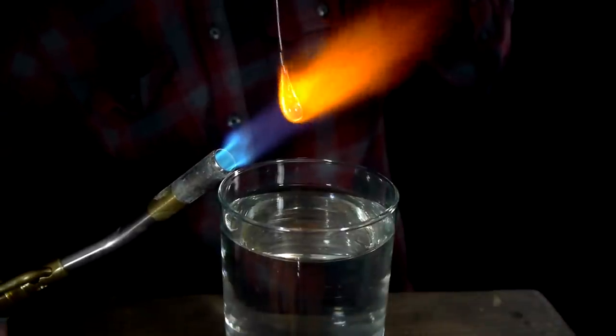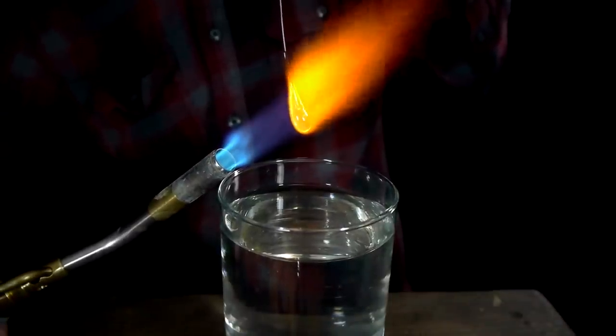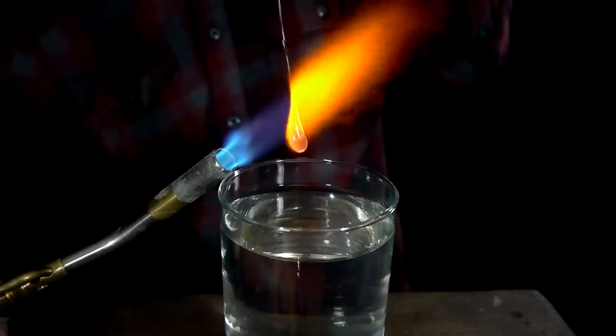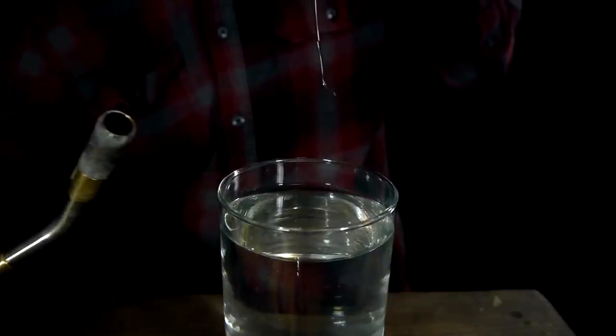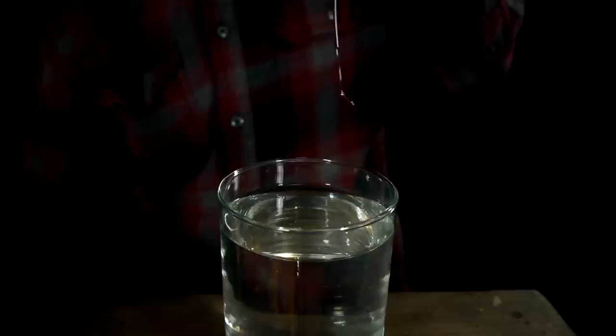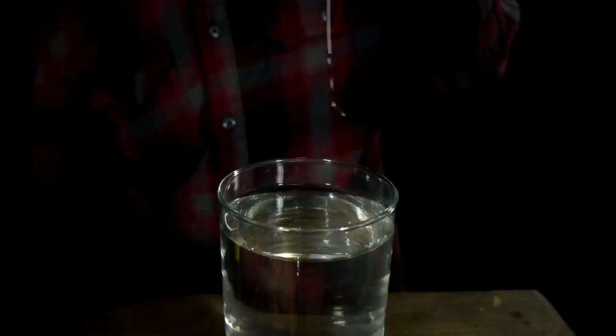When heated from the base of the drop with only a small amount of heat focused on the strand, the glass will eventually break free and fall into the cold water. There is still some chance that the drop may shatter, but it should survive the majority of the time if it has been heated correctly.